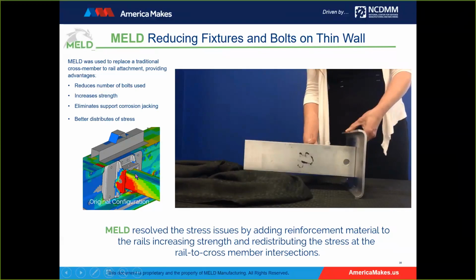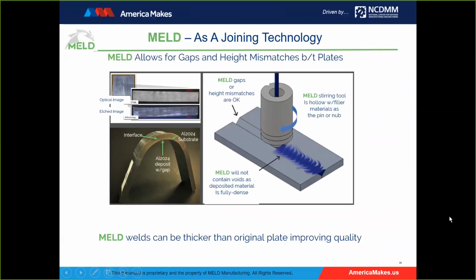We weren't permitted to show that slide, but you see the prior original configuration, and now with MELD, again, we just added a bunch of material, joined it to the rail through that same opening here. And we also addressed some corrosion jacking, again, because we deposit fully dense material. There's no ability for that corrosion to work its way into and through the surface. See if I can get to the next slide.